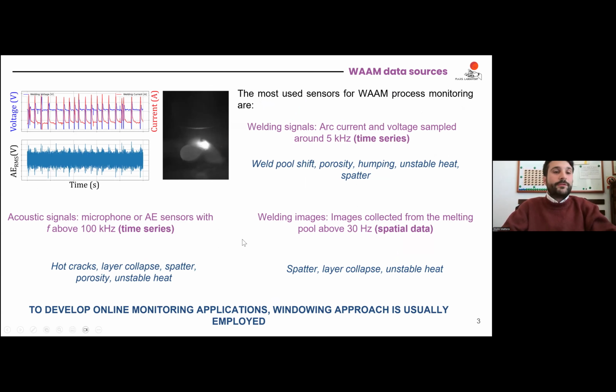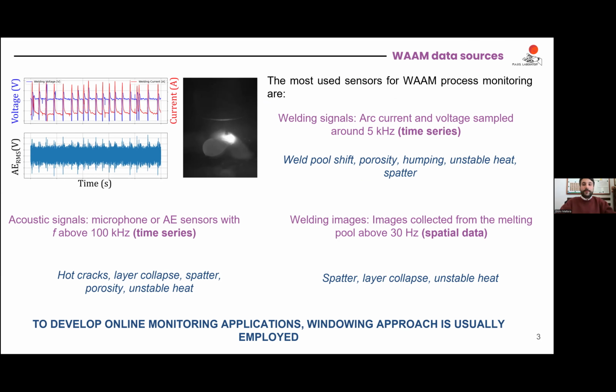Now, when you are trying to monitor the wire arc additive manufacturing process, you can rely on really several kinds of data sources. And every data source allows you to detect potentially different kinds of defects. So you can use welding signals, and by welding signals I mean the welding current and welding voltage acquired at high sample frequencies to collect pool shift or arc shift that maybe can cause layer collapse, porosity, humping, other problems like spatter and the unstable heat input during the process. And as material scientists, all of you know how important it is to maintain a stable heat input during the process for stabilizing the thermal behavior of the metal and for the microstructure. And you can do it just monitoring this signal.